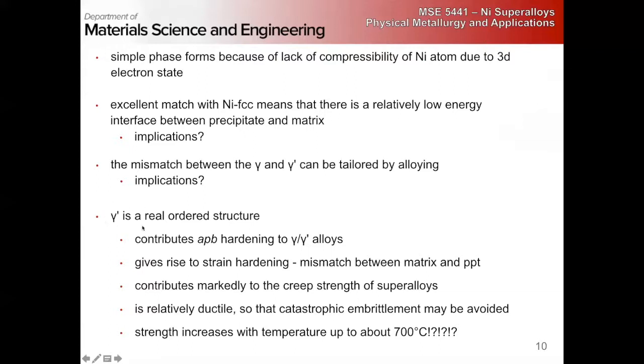Gamma prime is a really ordered structure, right? But it also is relatively ductile, right? So dislocations can move through it, it has a fairly low Peierls stress, right? We don't have to worry about catastrophic embrittlement, right? Which is really nice.